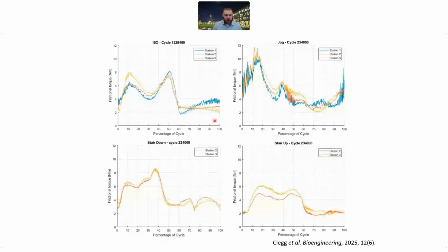When we look at just the ISO versus the jog cycle, we can see a much higher single peak in resultant torque, compared to a lower peak versus the ISO, and ultimately a lower swing phase, but this higher single peak in torque resulted in the increase in wear rate that we observed.